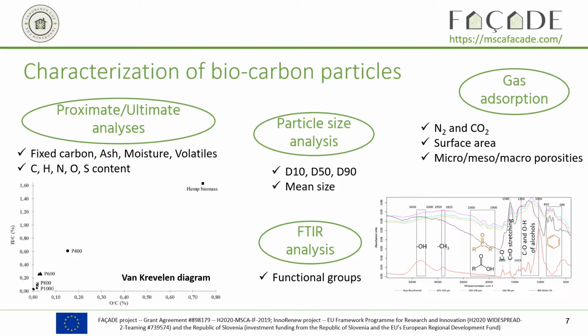We can also measure the particle size, so measure the D10, D50, D90, and the mean size of the particles. We have gas adsorption, so with two different gases, nitrogen and carbon dioxide, we can get the surface area of the biocarbon and also the distribution of the pores, and define how much micro, meso, and macro porosity we have in the material. And the final analysis will be the Fourier transform infrared spectroscopy. And we can get to the functional groups that will be at the surface of the material.